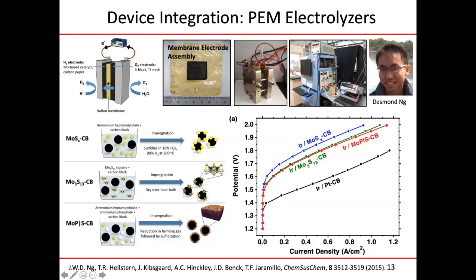And not surprisingly, the platinum iridium is the best. We know that platinum and iridium are the best catalysts for use in these types of devices, so that's not surprising. But what was really good to see is that these different non-precious metal formulations, when you replace the platinum with them, they still work. They still can get you your amp per square centimeter. And lo and behold, you have to pay about a 200 millivolt penalty to get the same current density.